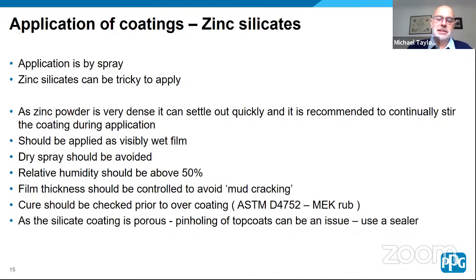You should apply zinc silicate as a visibly wet film. It's quite easy to get it to dry, to what we call dry spray. That's where basically the coating dries in the spray fan before it hits the object that you're coating, so it arrives on the surface as a powder with no cohesiveness to it at all, and you usually brush it off with your hand. You notice on your hand a grey dust, so it's important you get a visible wet film.